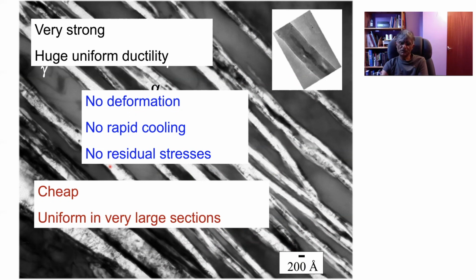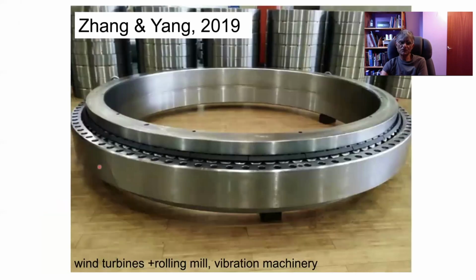Now, there is another application, which is also an important application. So this is a very large bearing for wind turbines. And the rolling elements that you see here, they are made out of the nanostructured bainite. Obviously, there are many variants today of the nanostructured bainite, so it isn't the composition that I showed you earlier, but this is an actual bearing with the nanostructured bainite rolling elements. Now, at the moment, the factory concerned doesn't have a facility to make such large rings using the heat treatment required, but they can make smaller bearing rings by the same concept. And that is work in progress.